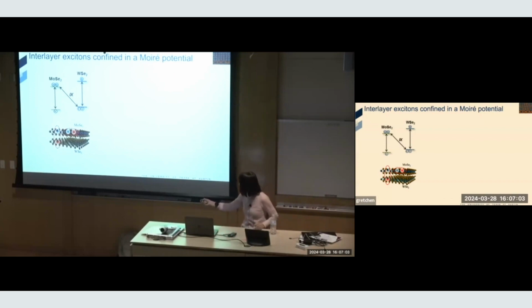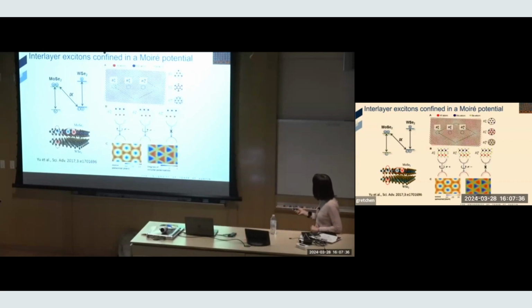The intralayer exciton, it's amazing. You take a single layer, you shine light on it, 5 to 8% of light resonant with the exciton energy gets absorbed. So they absorb light very strongly, just a single layer. By virtue of that very strong light matter interaction, they have a very fast radiative decay on the order of a picosecond, right? They go very fast, and these folks go much slower, starting with a nanosecond. As I can show you, they can be much longer, depends on how you control the twist angle.